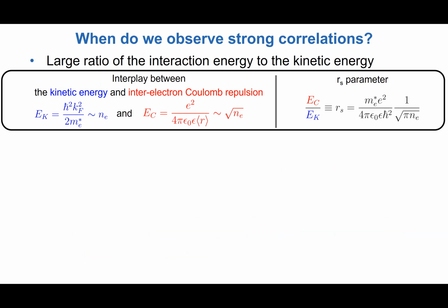So basically, we can hope to get strong correlations when we have a system with a characteristic interaction energy scale. We are considering charged particles, electrons with a certain average separation R, and so the two energy scales that are relevant are the Coulomb repulsion between two electrons, given by this expression, and the characteristic kinetic energy of the electrons that comes from the fact that they are fermionic particles and Pauli exclusion requires that we can put only one electron in any given quantum state. What you will see then in 2D is that the kinetic energy scales as the electron density, whereas the interaction scale goes as the square root of the electron density.